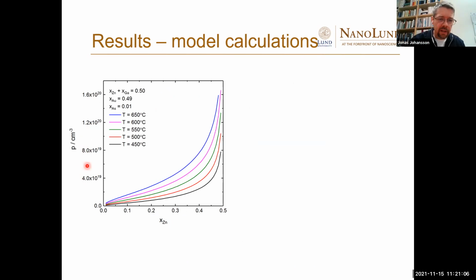So the hole concentration as a function of zinc molar fraction in the liquid droplet. So here zinc and gallium is 50%, gold is 49%, and arsenic is 1%. So I tried this at different growth temperatures, and you see that when we increase the zinc concentration, the zinc doping increases steeper and steeper, and it also increases with temperature.